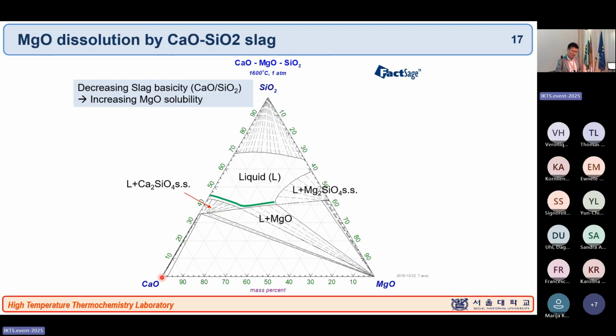So if you look at here, this is pure CaO, pure SiO2. So the SiO2 content is changing 10, 20, 30, 40. So it means here it's about 50% of SiO2, okay? And now if you look at this axis, the MgO content is changing from 0, 10, 20, 30, etc. So it means at this point you have about 10% of MgO, and the rest of it would be CaO concentration. Okay, so that's how we read it.